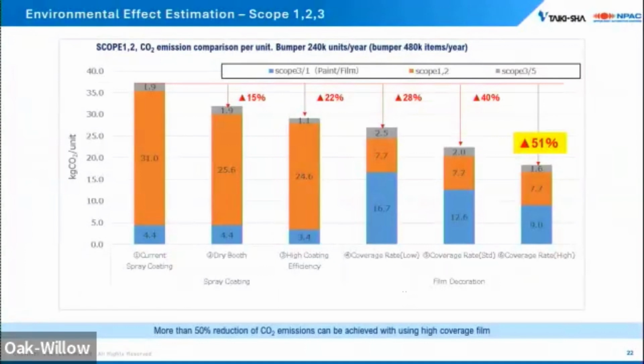We've added that in. In blue, you'll see the Category 1 emissions from the paint or film manufacturing, and then gray is the Category 5 contribution from waste paint or waste film. And you'll see that the emissions from the dry film manufacturing process still plays a significant part of the equation. And even assuming the lowest coverage ratio or the most waste film, we're still seeing a 28% drop in CO2 emissions compared to conventional processes.